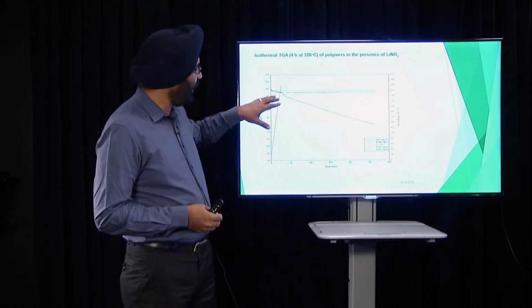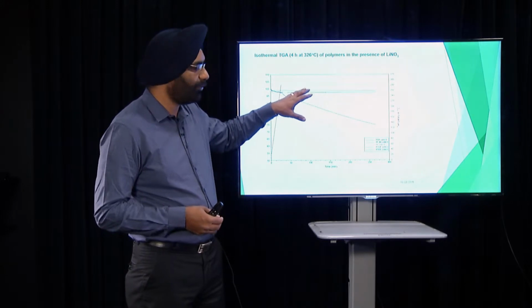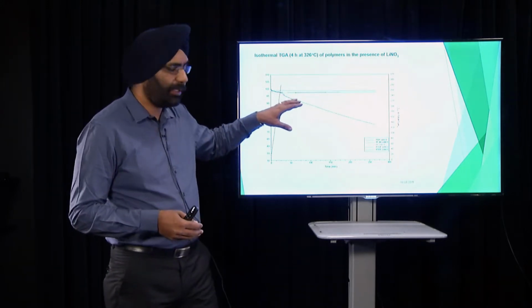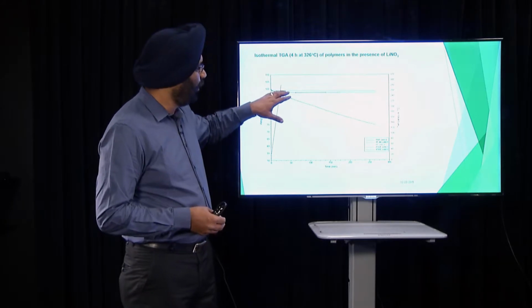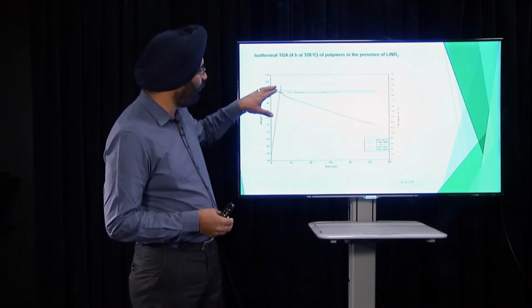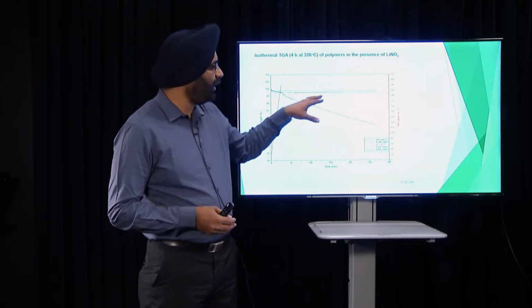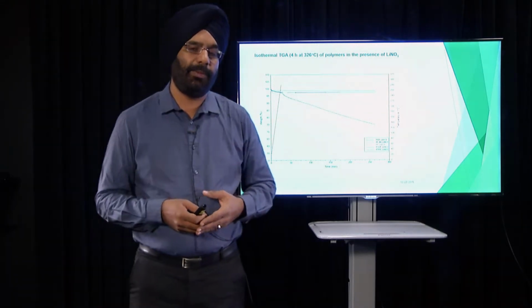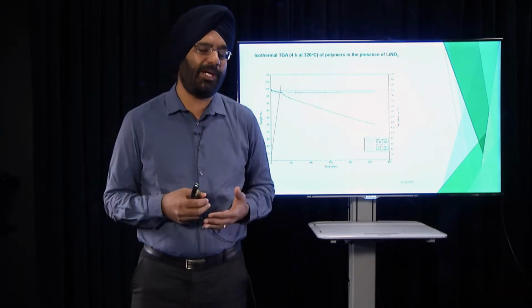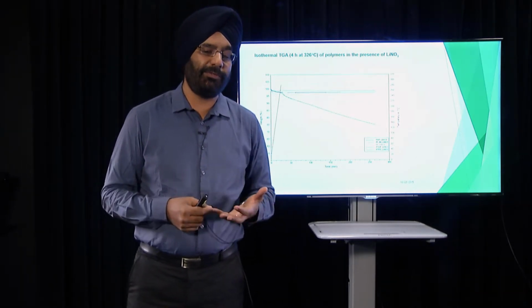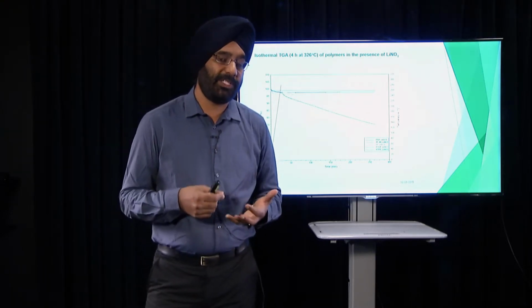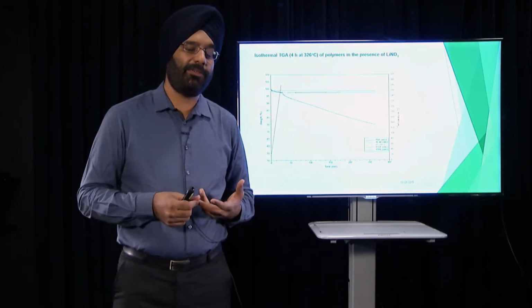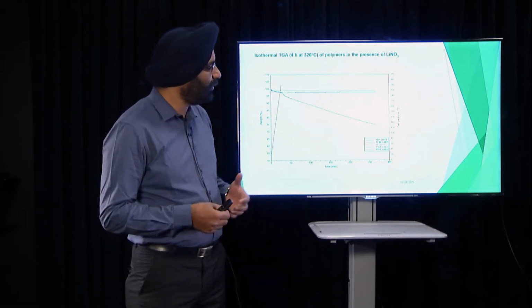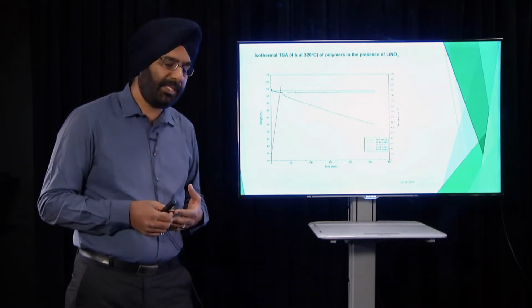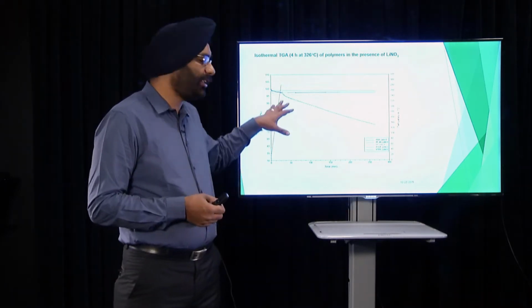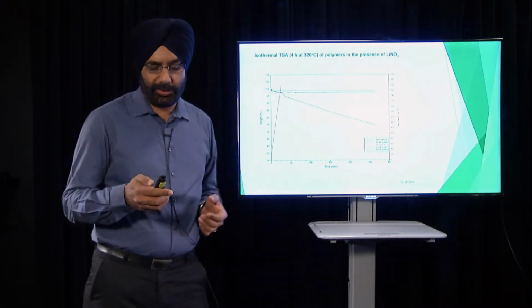The other material which we selected here, the green one, for some proprietary reason I am not going to tell which material we used. As you can see, over a very extended period of time, the green one didn't show any weight loss. That means it's perfectly compatible with the phase change material. So that's how we solved the chemical problem. We solved the physical problem by selecting polymers which are flexible and selectively permeable, and we solved the chemical barrier by carrying out compatibility studies involving thermogravimetric analysis, where we selected a material which didn't show any reactivity with the chosen phase change material.